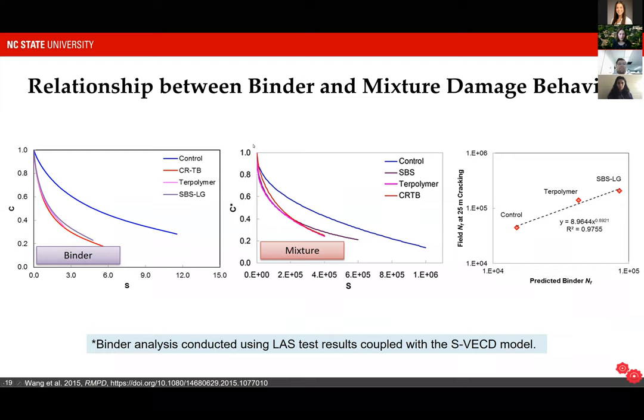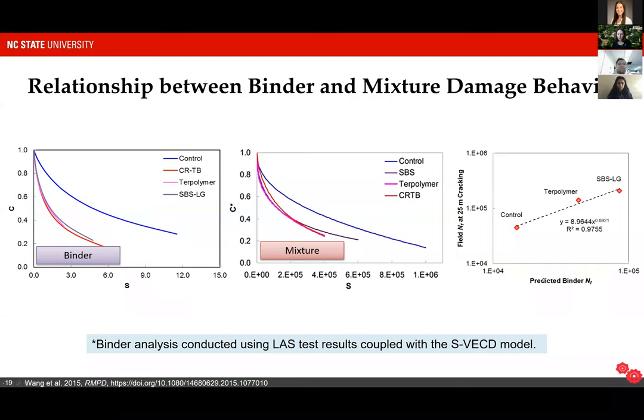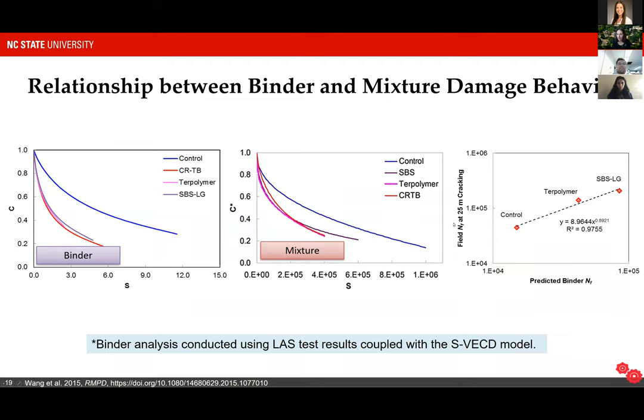Despite this, the results do suggest quite good promise even when we neglect the effects of viscoelastic non-linearity for reflecting mixture cracking performance. We've shown very similar trends in terms of binder damage characteristic curves versus mixture damage characteristic curves, and we've also used the LAS test results coupled with the SVECD model to generate fatigue life predictions that correlate well with measurements of field fatigue life at the Federal Highway Administration's accelerated loading facility. We've seen quite promising results in capturing at least the relative rank of cracking resistance of different binders using this framework.